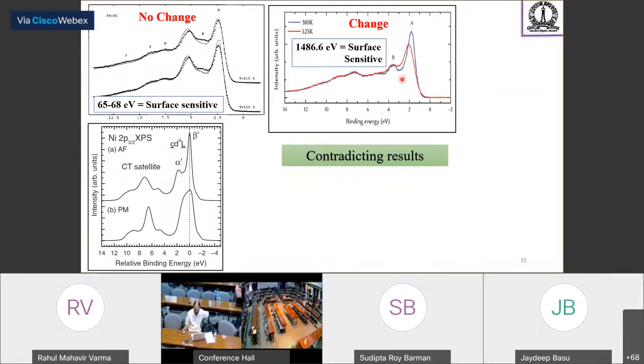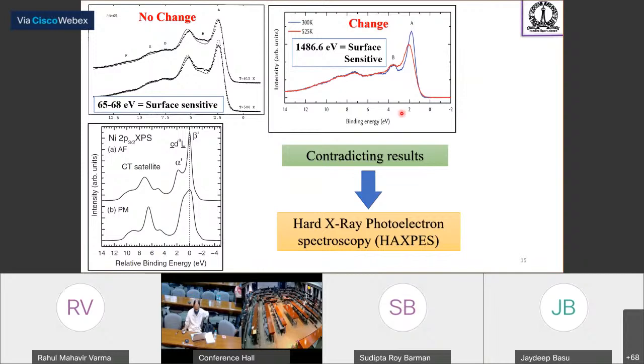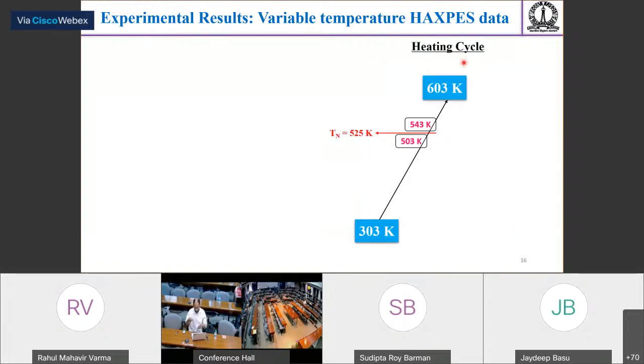So to realize the origin of these changes, we have done hard X-ray photoemission spectroscopy, which is bulk sensitive and the ideal tool to investigate this issue. We have performed variable temperature HAXPES measurements at beamline P22 at PETRA III, and we have performed a full heating cycle starting from room temperature, going up to the highest temperature available at the beamline, that was 603 Kelvin, which is far above the transition temperature.